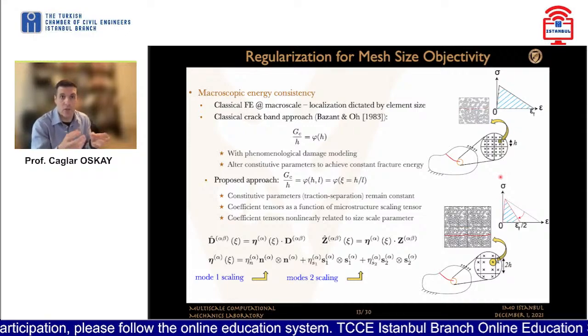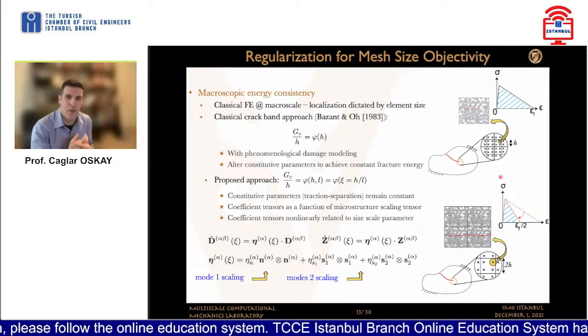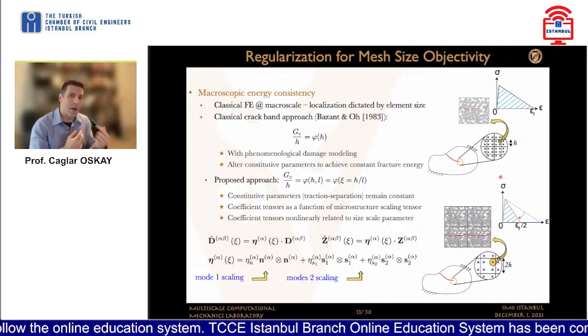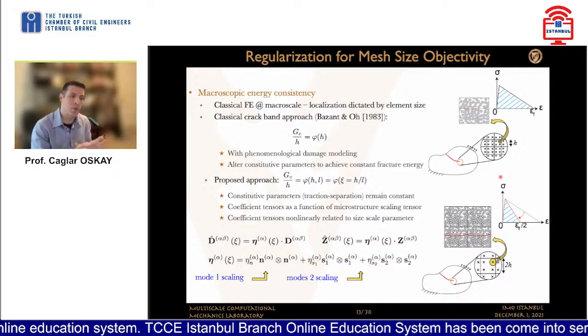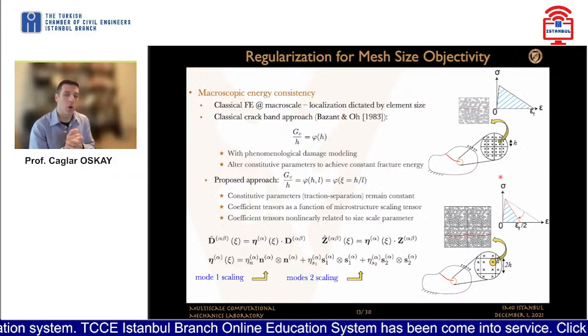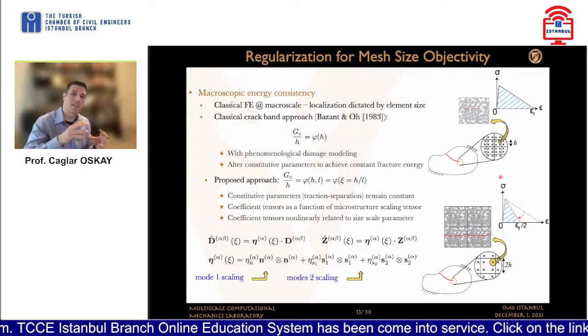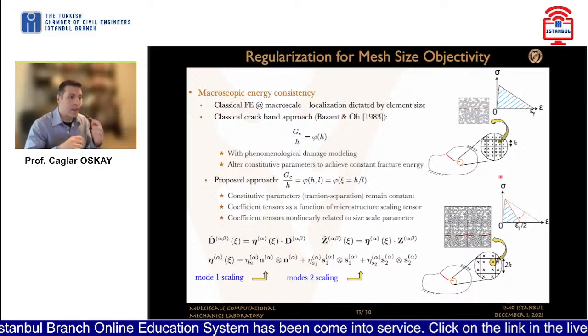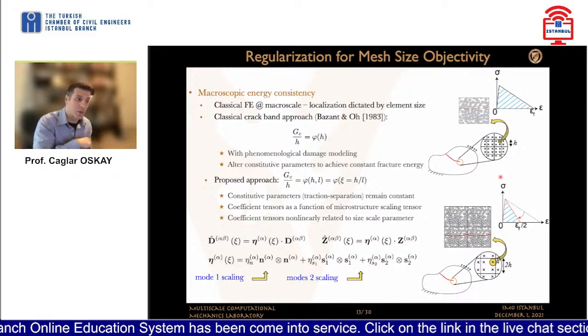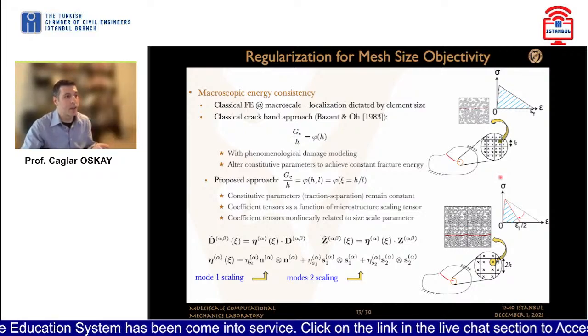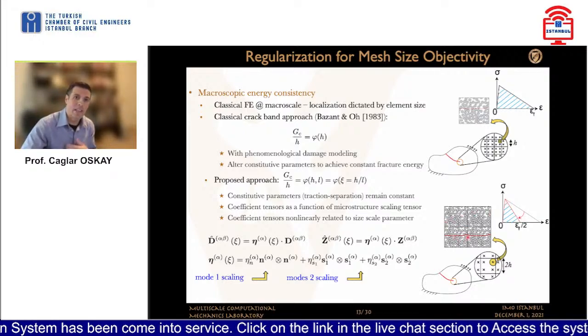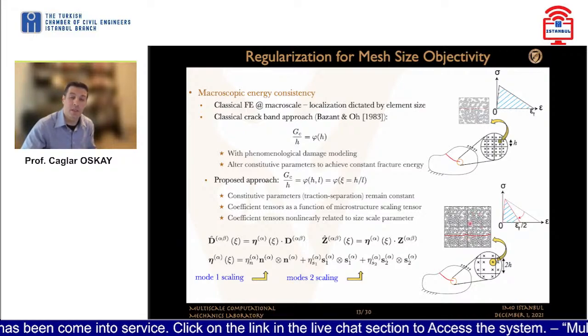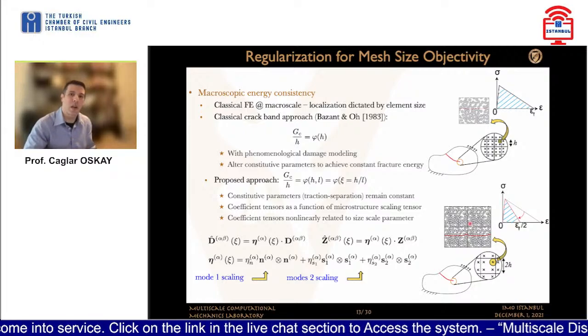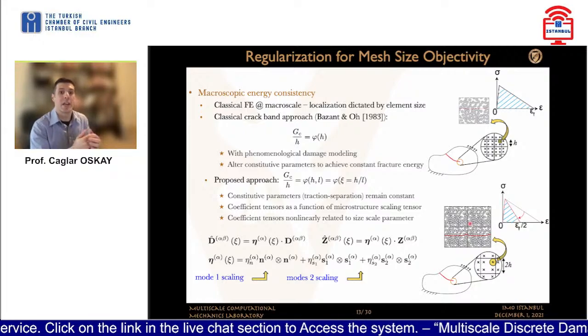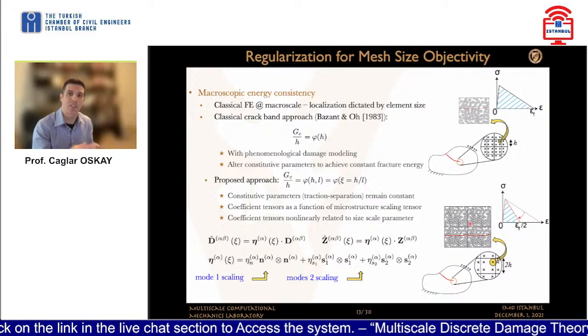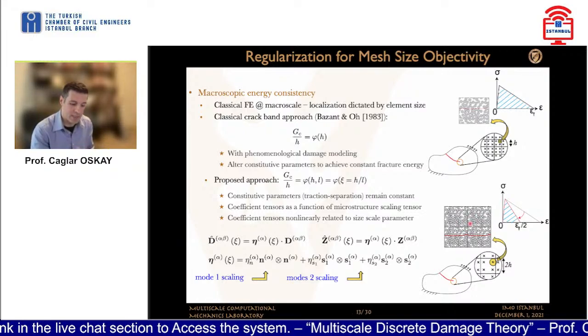Now, the problem here is that you need to adjust the material parameters. The question is, what kind of material parameters do we need to begin with then? So in our approach, let's keep the constitutive parameters, which are the traction-separation behavior, the same. What we're going to change is the size of the microstructure as a function of the size of the finite element that we're using. And we can do that very easily because of the analytical relationships that we have observed previously. By this approach, we're going to again keep the overall fracture energy constant by automatically adjusting the size of the microstructure as a function of the element size. So the answer to the previous question was, it's essentially an adjusted microstructure. The size is adjusted, which happens to alleviate the mesh size sensitivity issue as well.